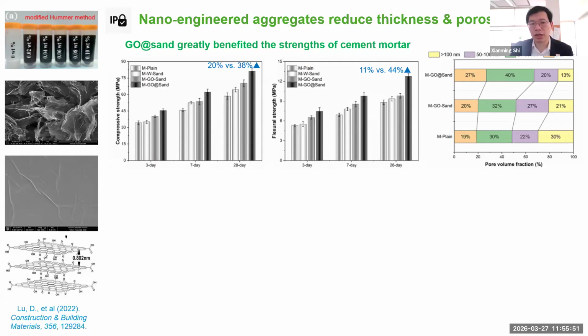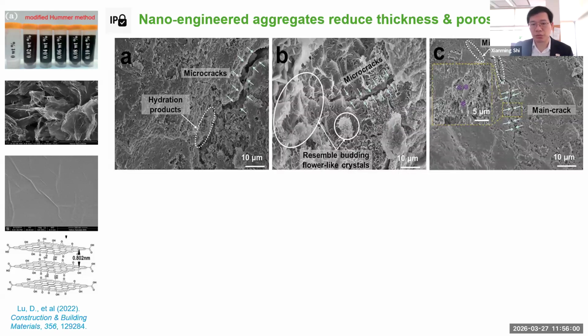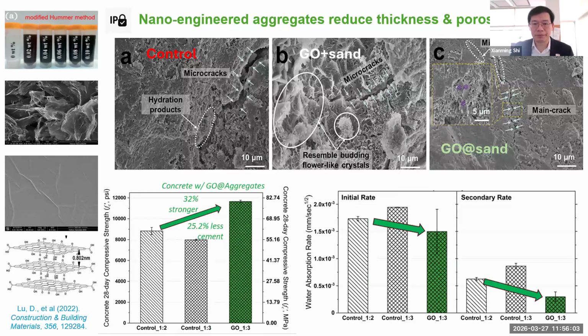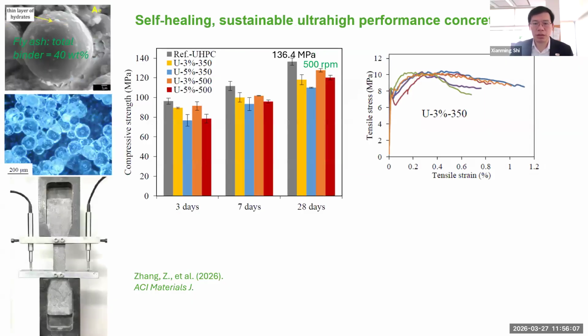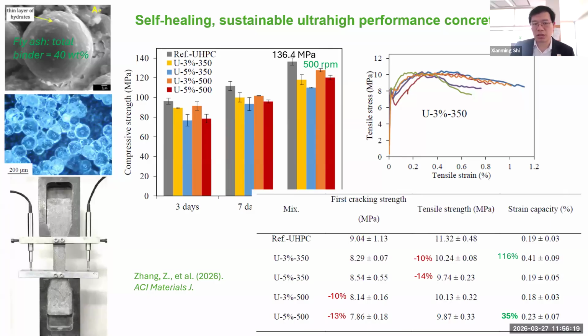For instance, like this one, we have another patent, which is pre-treatment of sand and gravel, and then you can achieve significantly better strength and durability with a very simple treatment. Yet another one is self-healing UHPC, or ultra-high performance concrete. We produce these microcapsules, and we demonstrate you can enable much better self-healing in UHPC. And again, the next step, instead of using microcapsules, we're using biochar as the carrier of the healants. We have another patent just filed last week, basically demonstrating we can use biochar as a carrier for healants.